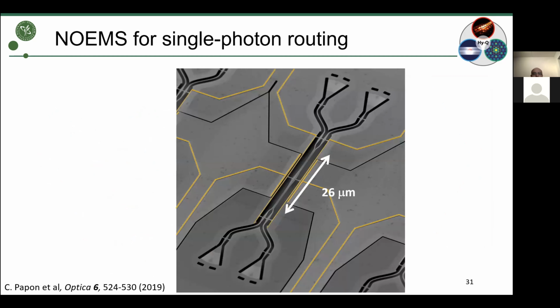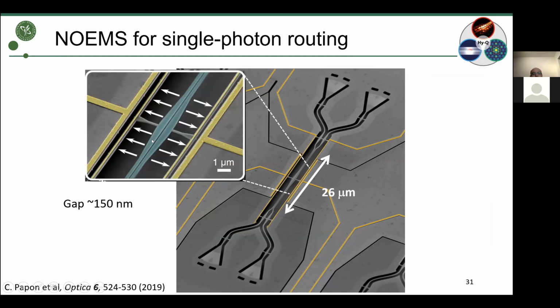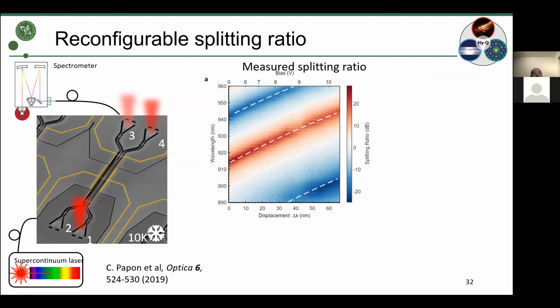So we have built a device like this, and this is the one I was showing at the very beginning. This is fabricated in the same platform that I was showing you before. And what we have realized here is indeed couplers and waveguides, and then everything is suspended with tethers, and there are quantum dots in it. And then light enters into this region, and if you zoom in, you actually see there are two waveguides here that are very close to each other, 150 nanometers apart. And there are these two sets of electrodes here on the right and the left that are biased to a particular voltage. And as soon as you do that, you apply a force, and this force pushes the two waveguides apart. And so you can control the distance between the two waveguides and tune this device on the fly.